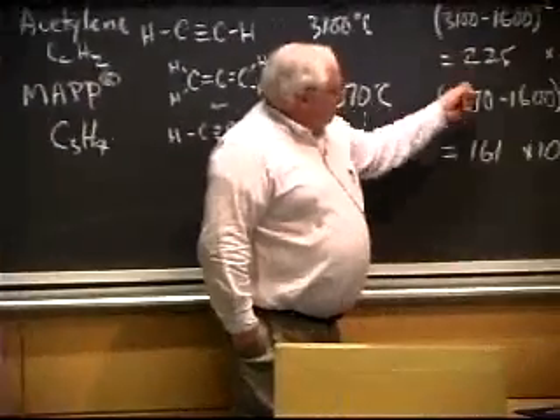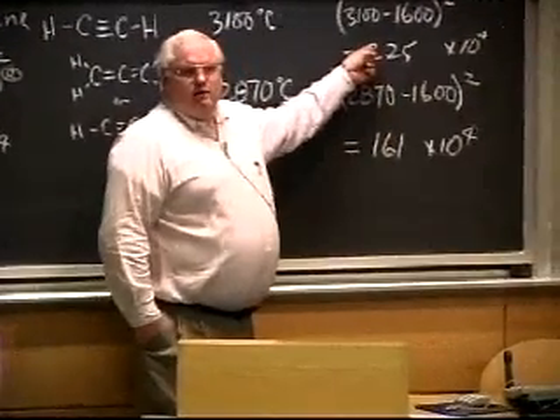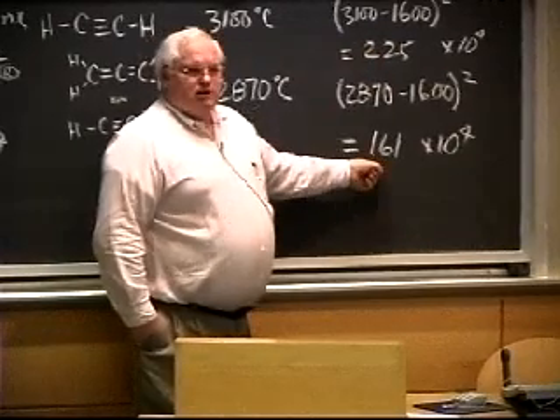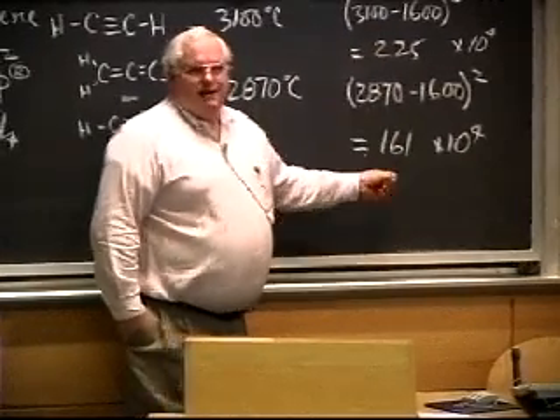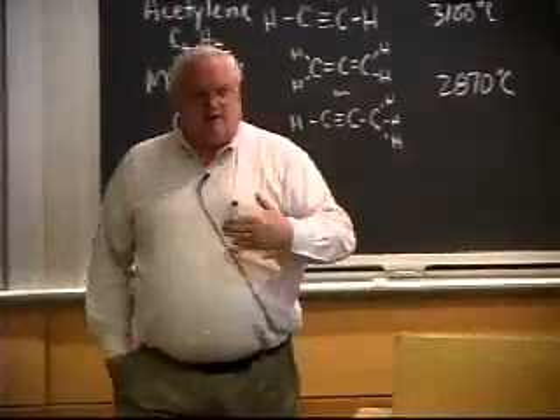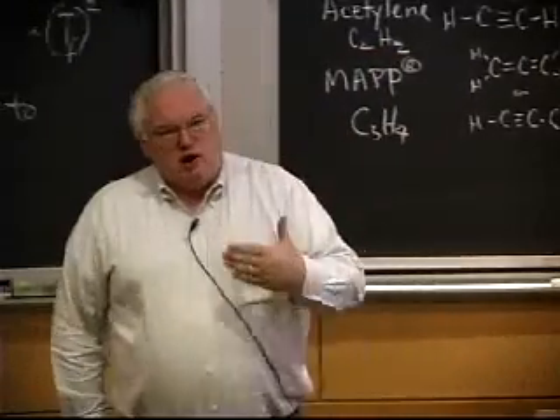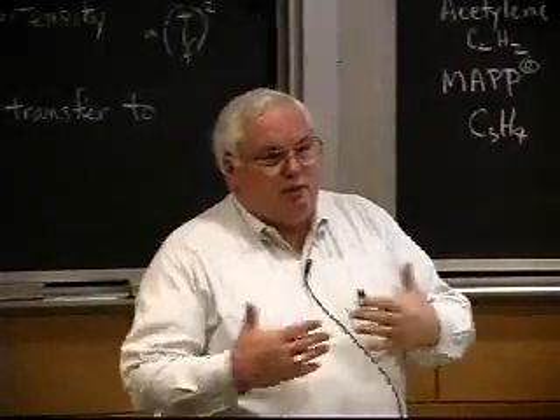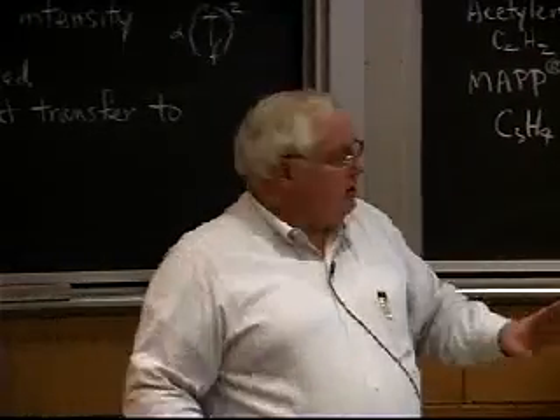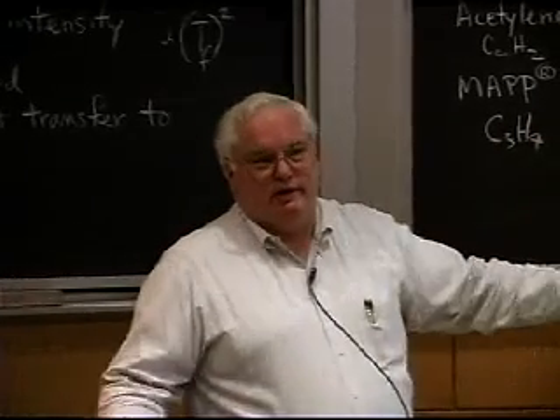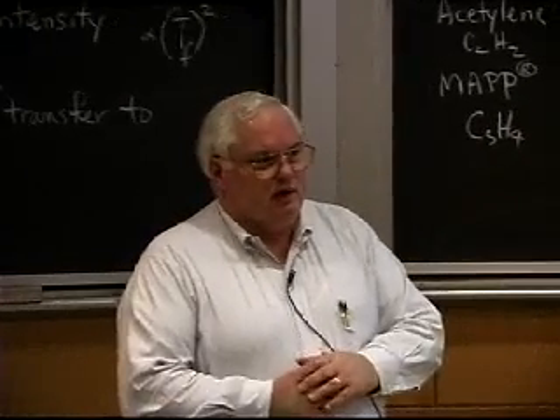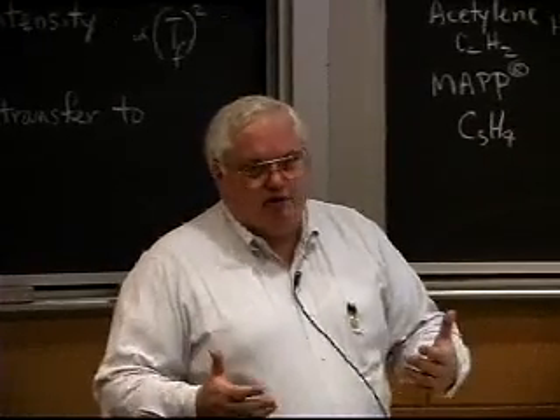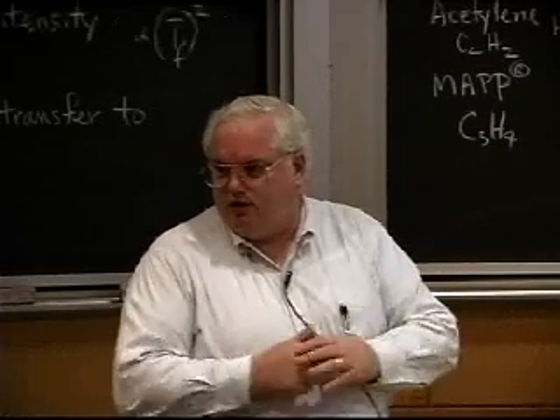It turns out there's a 30% decrease, if you will, in the heating value of MAPP versus acetylene if I'm trying to melt steel. If I'm just trying to heat up cold steel, there's hardly any difference at all, because it's going to be 3,100 minus, what, 20 degrees C versus 2,870 minus 20 degrees C, and you square those and there's not a big difference.